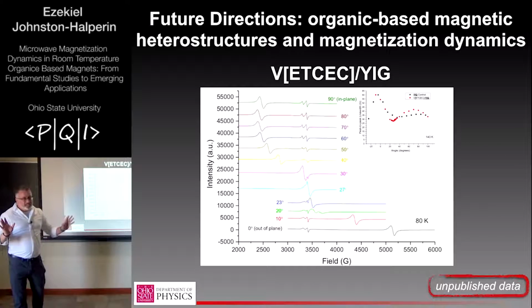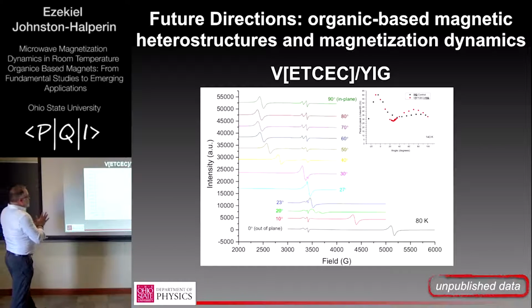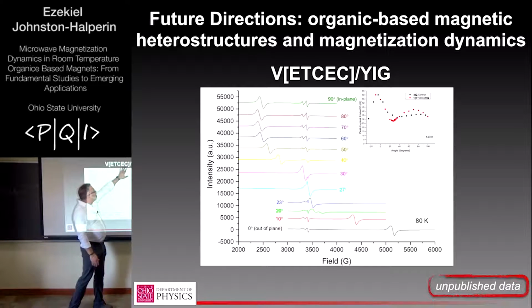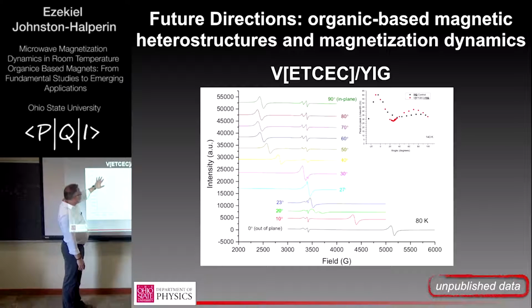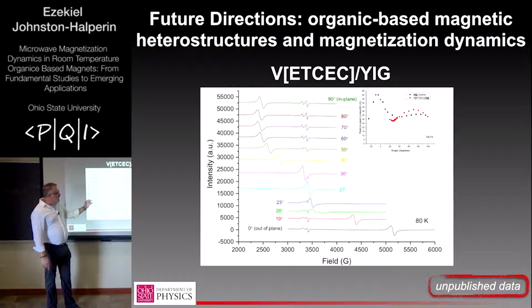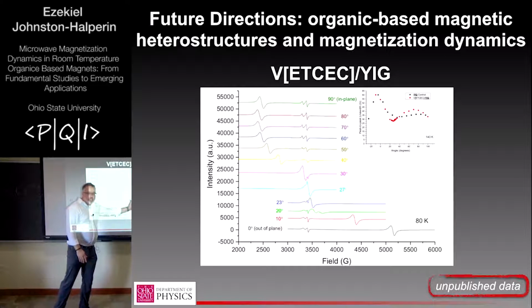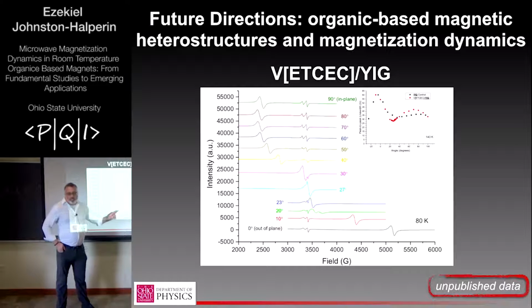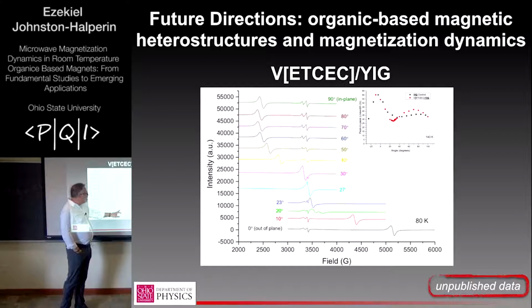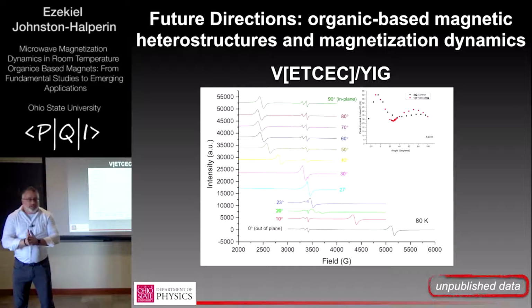Now just two slides of very speculative preliminary stuff. We can make heterostructures of this. This is not VTCNE, but ETCEC for historical reasons. We were, as usual, making the sample for other reasons, but putting it on top of YIG. Then you can play a trick where you vary the in-plane angle, and YIG has a larger magnetization, so it will tune much more broadly as you vary the angle. We can walk the frequency of the YIG resonance directly on top of the frequency of the organic resonance. When we do that, you can see the line shape changes dramatically. These additional peaks from the organic disappear, and the resonance, at least this half of the resonance, sharpens up. This is a very clear signature of resonant coupling between the two magnetizations.